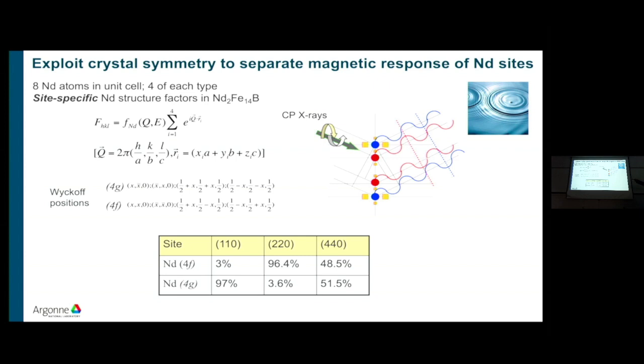So in a simple picture, at a particular Bragg condition, you can have constructive interference for the blue atoms where the scattered waves interfere constructively, so you have a strong Bragg peak from these atoms, but at the same time, the diffraction from the other sublattice vanishes or goes very weak.